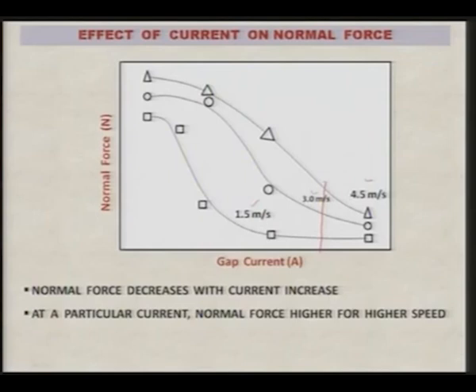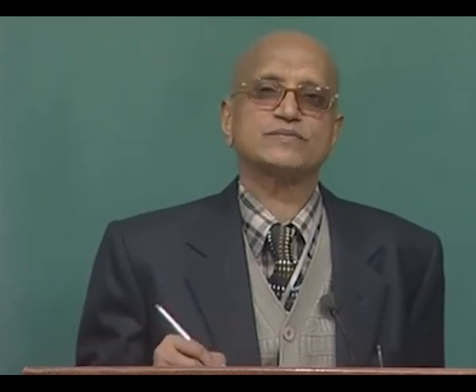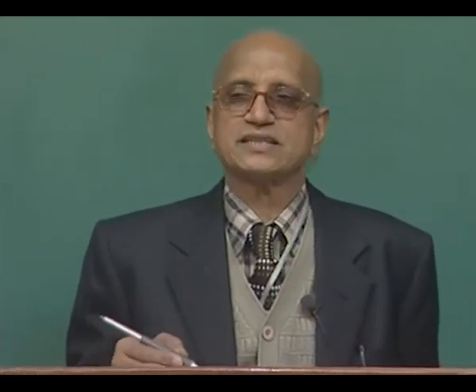The reason is very simple: as speed increases, the time for the heat to soften the workpiece is low, and if the time for the heat to penetrate inside the workpiece and soften it is low, then definitely its hardness will be more, and if hardness is more, then the normal force for penetration of the abrasive particle inside the workpiece will be more.